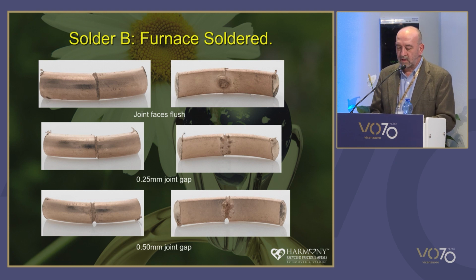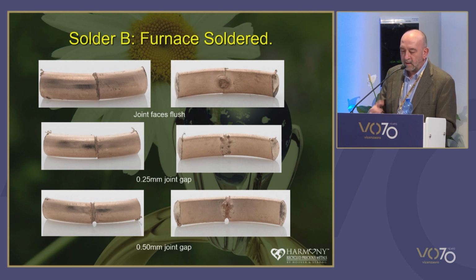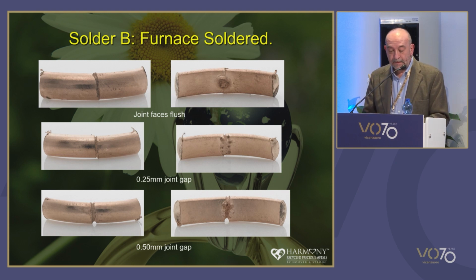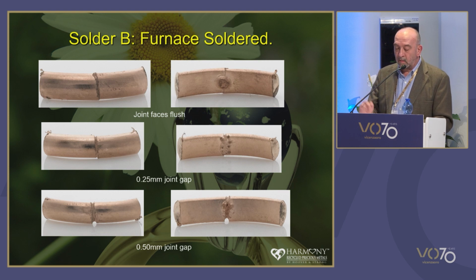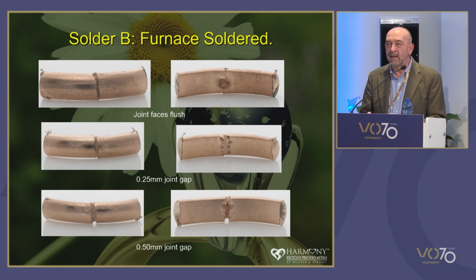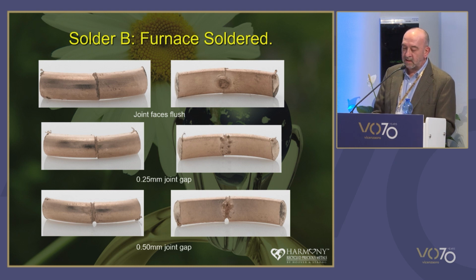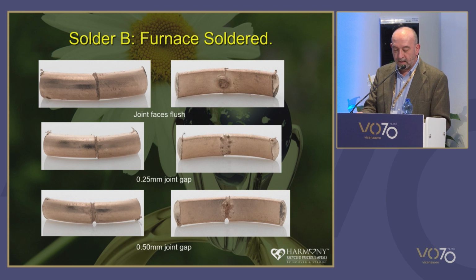The results also suggest that furnace soldering is going to be more susceptible to things like varying thermal loads on the furnace. So the 4th test we did was to solder a post on top of a cup setting to make earrings, and this is a textbook example of a T-joint. We used the same test criteria for torch and furnace soldering, and we tack welded the post on top of the earring before applying any solder.